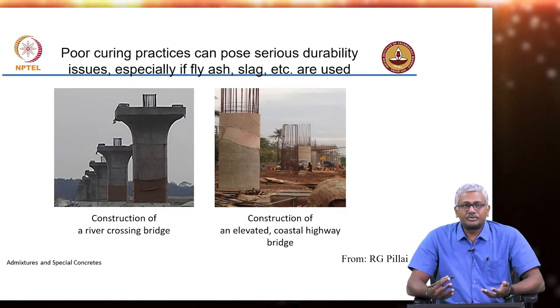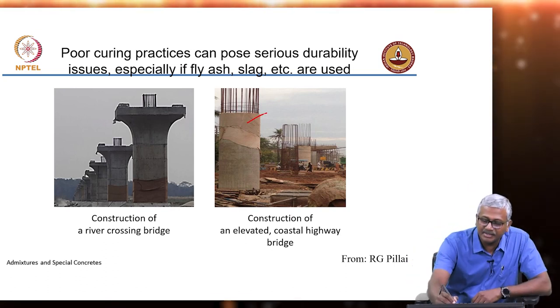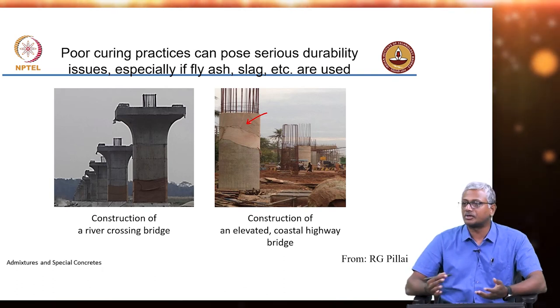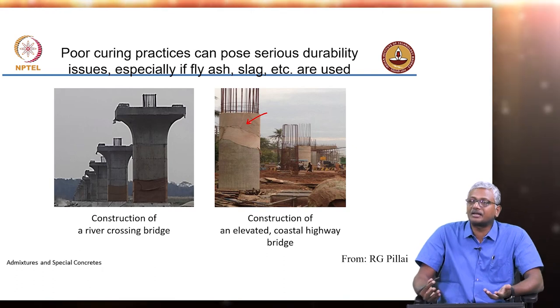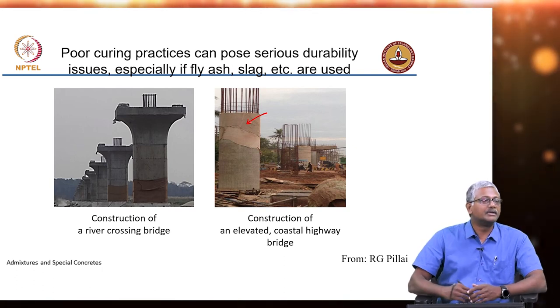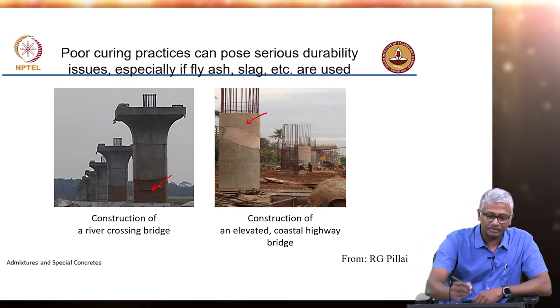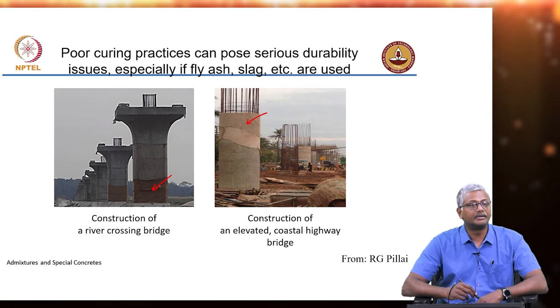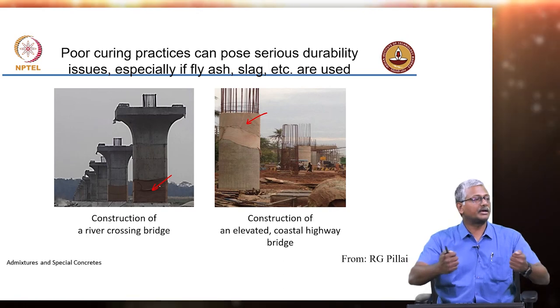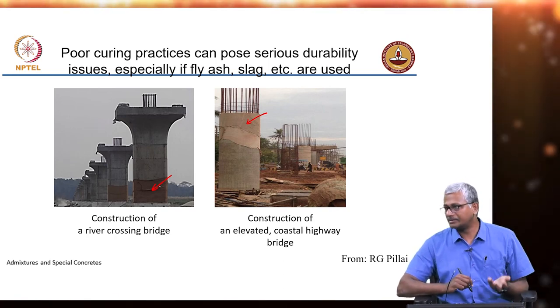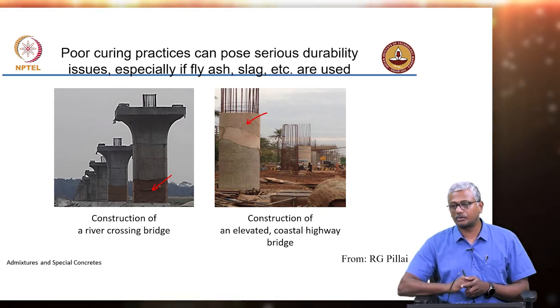On our sites, curing quality is typically very poor. You see Hessian cloth covering the concrete surface, but it is not wet at all — it is completely dry. If it is dry, there is no water supplied from the outside environment, so water is going to start drying out from the concrete and you are going to get very poor curing. When you are using Hessian or jute cloth covering on the concrete surface, it has to be kept wet all the time — only then will it protect the concrete and provide sufficient curing.